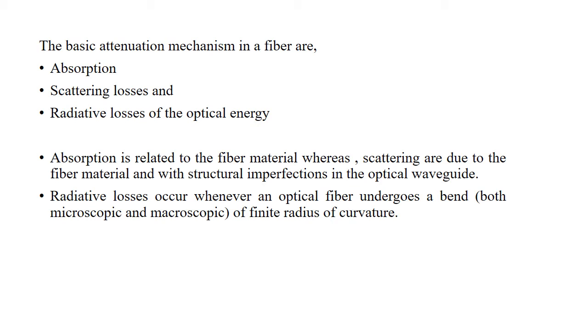The basic attenuation mechanisms in a fiber are absorption, scattering losses, and the radiative losses of the optical energy. Normally absorption is related to the fiber material, whereas scattering is due to the fiber material and the structural imperfections in the optical waveguide. Radiative losses occur when an optical fiber undergoes a bend of finite radius of curvature.